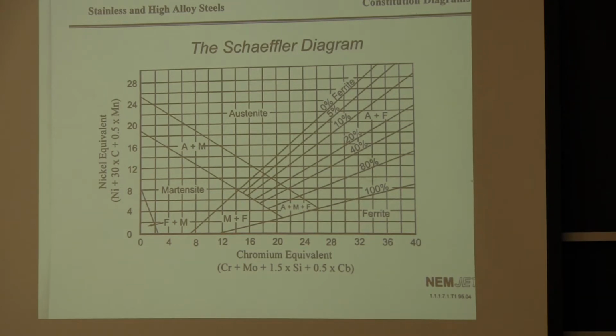And if you look at the axes, you've got a chromium equivalent along the x-axis and a nickel equivalent along the y-axis. And what they've done is they've taken the various alloying elements that you might find in your stainless steel, and they've basically, what's the right word, made them equivalent to either chromium or nickel. And so in doing the research to develop this type of diagram, you have to determine, for example, on the nickel equivalent, that carbon is about 30 times more potent in forming austenite than nickel is, whereas manganese is about half as potent.